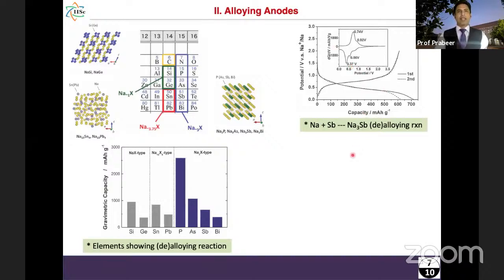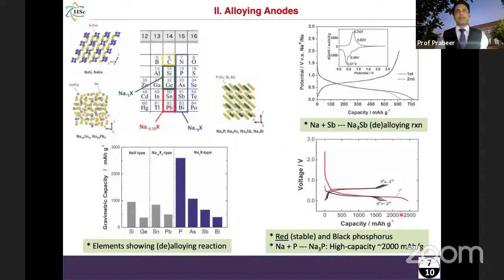And the most important example here is phosphorus. Phosphorus basically exists in 3 forms: the amorphous form, the red phosphorus, and the black phosphorus. The red phosphorus is very, very stable. And once again, when we use just red phosphorus, it can react with sodium to form Na3P. And because phosphorus has a very, very low weight, it can give rise to very high capacity, around 2000 milliamp per gram. So these are some examples where we can use these group 14 and 15 elements to design some alloying and de-alloying kind of anode materials.